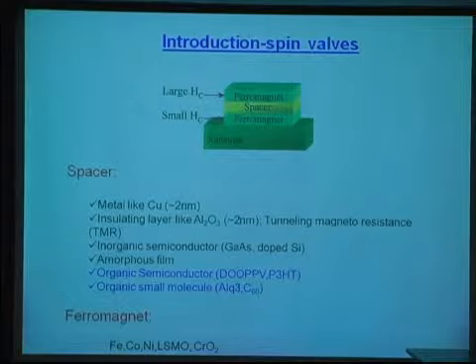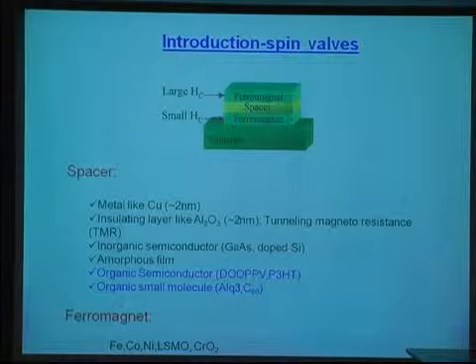Okay, so here is the schematic of the spin valves in general. They have a spacer sandwiched between 2 ferromagnets with different coercive fields. One is large and one is small, and the spacer here can be copper, can be an insulator like aluminum oxide, can be an inorganic or organic semiconductor, small molecules, something like that. And the ferromagnetic electrodes can be iron, cobalt, nickel, and those materials have different spin polarization, different capability to inject the spin-alike carrier into the organic semiconductor or the spacer.